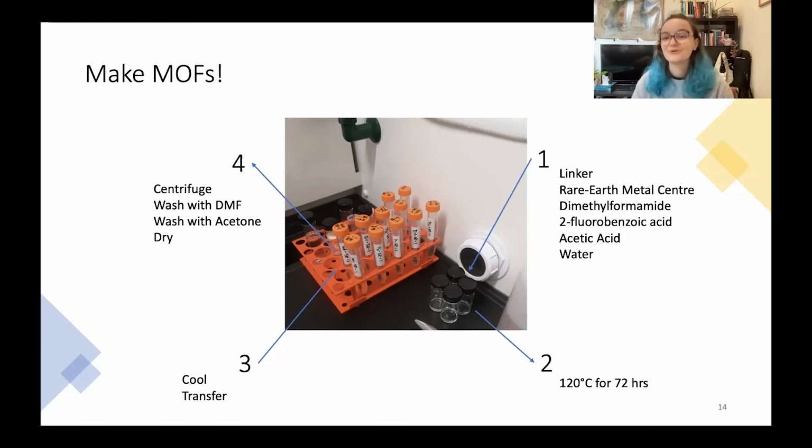So again, more wait time. Once they are done, we let them cool off and we transfer them to centrifuge tubes for the washing process. So we wash them with new DMF, or dimethyl formamide, to clean them out. And then we wash them with acetone to clean out the DMF. And then the acetone dries out and we have MOFs that we can use.